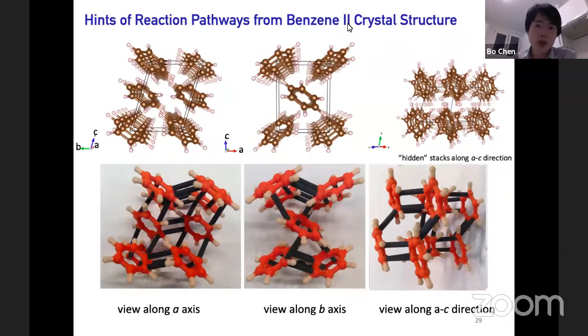Here we are looking at benzene II, which is a phase where the polymerization occurred. Along the A and B axis, we can see these benzene stacks. The benzene rings are parallel with each other, but their planes are not perpendicular to the axis. And there's another hidden stack along the AC direction, which you can also see here.